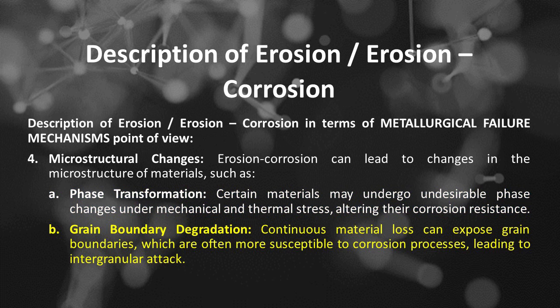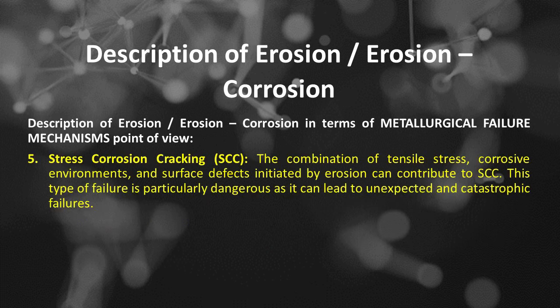The second is grain boundary degradation. Continuous material loss can expose grain boundaries, which are often more susceptible to corrosion processes, leading to intergranular attack. Number 5 is stress corrosion cracking, or SCC. The combination of tensile stress, corrosive environments, and surface defects initiated by erosion can contribute to SCC. This type of failure is particularly dangerous as it can lead to unexpected and catastrophic failures.